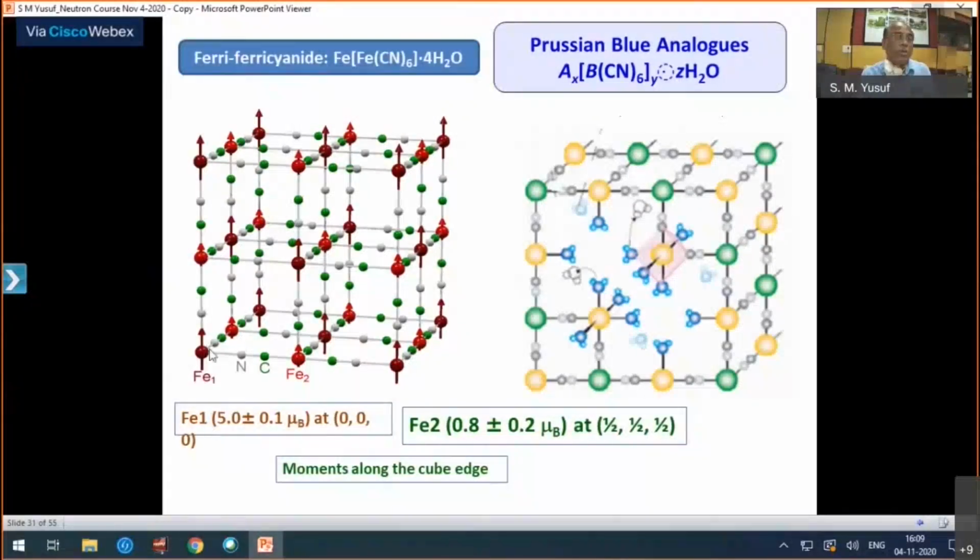So you can not only measure the magnetic moment; you also see that I have drawn one vector like this, and another vector is also parallel to that. That also comes from this diffraction. It tells me that they are parallel, so moments are ferromagnetically coupled. This is the microscopic picture of the so-called ferromagnetic ordering. When we do DC magnetization or any other bulk technique, we do not have any knowledge about this microscopic, atomic length scale information, about the vector orientation of these atomic dipole moments and their magnitude.